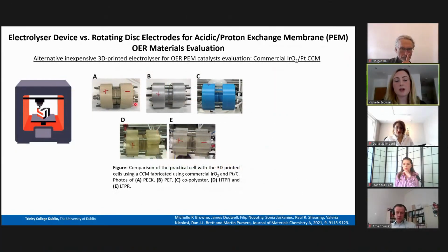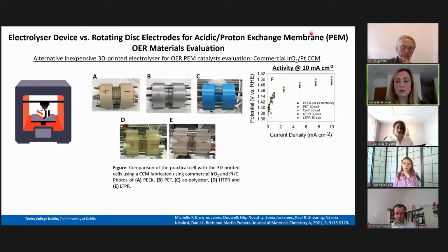that we used for the previous studies on the last slide. So to compare our 3D printed electrolyzers to our PEEK cell, we used a commercial iridium dioxide and platinum CCM or catalyst coated membrane materials. So if we look at the activity of the same CCM in all the different devices, we can see the activity is pretty good for all of them. So essentially you can use any one of these 3D printed electrolyzers to successfully evaluate the activity of your material.